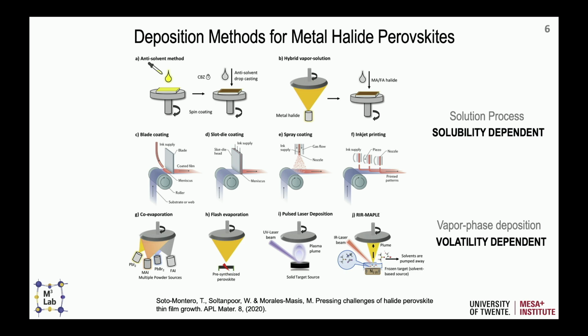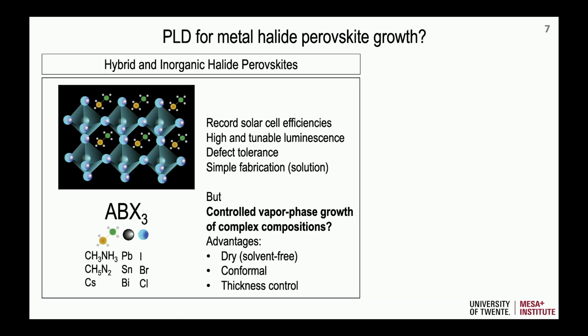Another process is something called flash evaporation. So what you do is you put all the powders and then you kind of explode them by putting a very high current, and they basically deposit. But it's still a thermal process, so it's very difficult to control the stoichiometry. And by looking at that, we went to, okay, let's look into pulsed laser deposition to see if we can overcome this volatility dependence. And we are not the only ones, there are other techniques that are laser-based to also grow these halide perovskites.